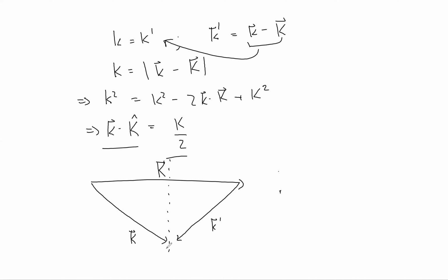And because these Bragg planes are planes perpendicular to reciprocal lattice vectors, they correspond, as you know, to real space lattice planes. So now you can start to see that there's a connection between this von Laue formulation and the Bragg formulation of X-ray diffraction. So we can see that they are, in fact, identical in the following way.